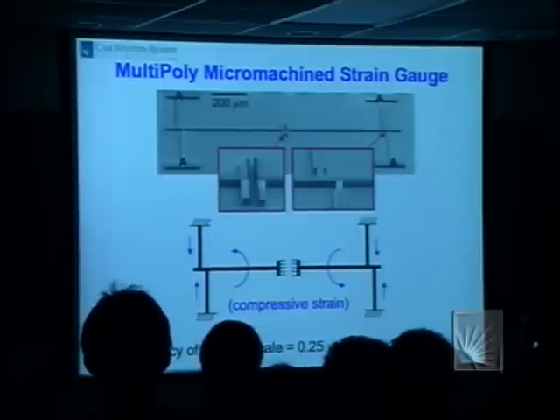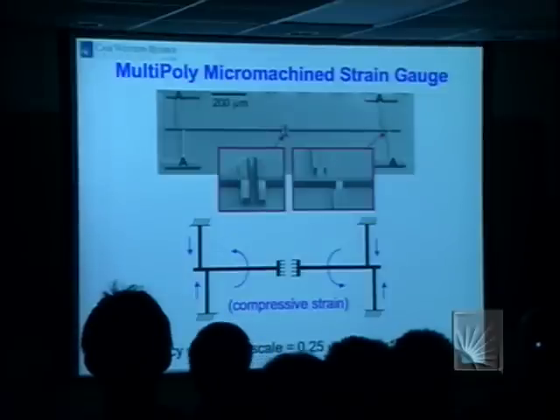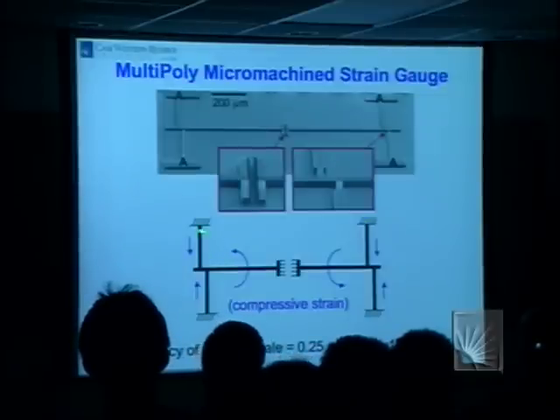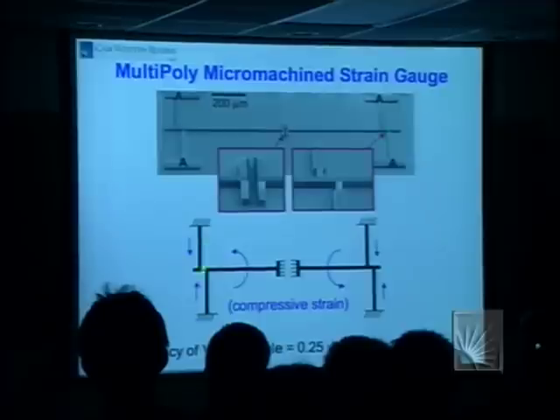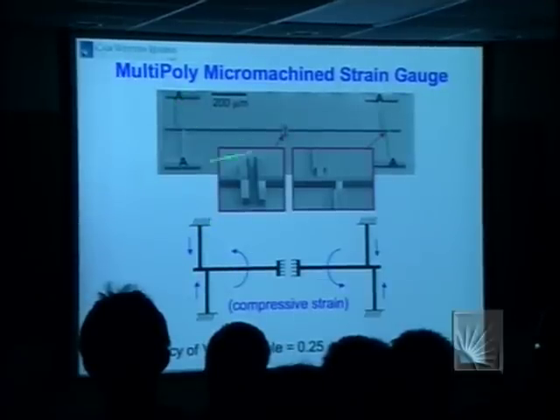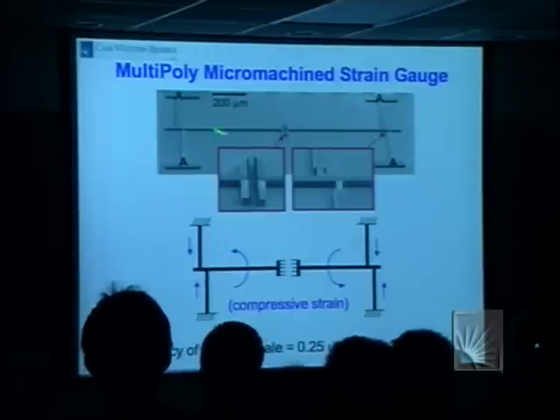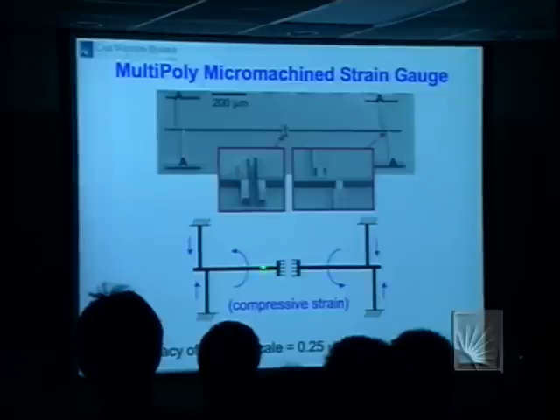So this is a micromachine strain gauge. As shown here, if there's compressive stresses in these four legs, these are the anchors. There's still some SiO2 pinning this to the surface. These are floating. And when you release this material, if there's a compressive stress in the film, you'll get the motion of these two verniers as indicated.